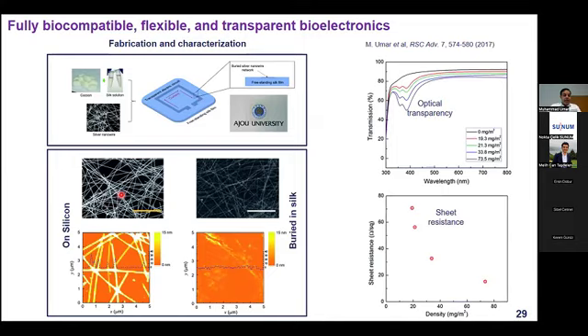If you see the SEM image on the silicon, we can see the silver nanowires on the silicon, and then the SEM and AFM images. But when we bury the structure into the silk, here is the SEM image and this is the AFM image. This AFM image shows that silver nanowires are fully buried inside the silk, and there is very low roughness of this surface. So this means it could be utilized as a seamless surface for biotic and abiotic interfaces.